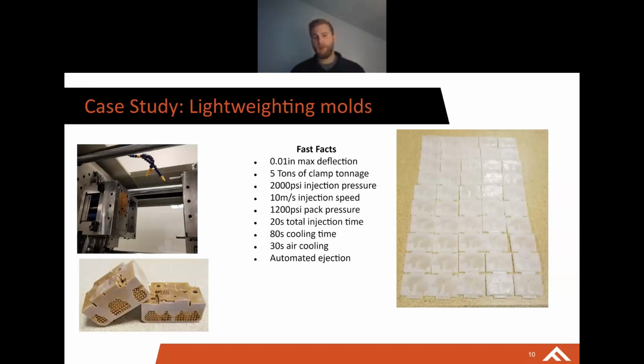We're using a 2,000 PSI injection pressure, and we are running a pressure limited process, meaning that once we hit that 2,000 PSI, we're willing to give up control of the speed. So for our press, which is a 30-ton Nissei with a 19mm barrel, we give up control of that 10 millimeters per second once we hit that 2,000 PSI. We're not in large-scale production, so having control of those variables doesn't quite matter to us as much as it does to get a nice defect-free part. And we find that for tool life, tool longevity, and part quality, this is the best way to run.